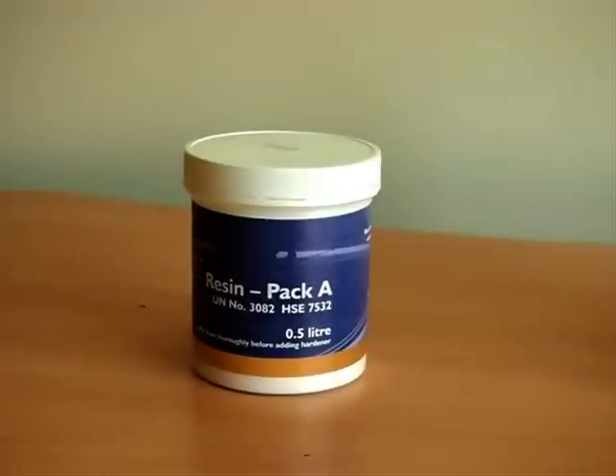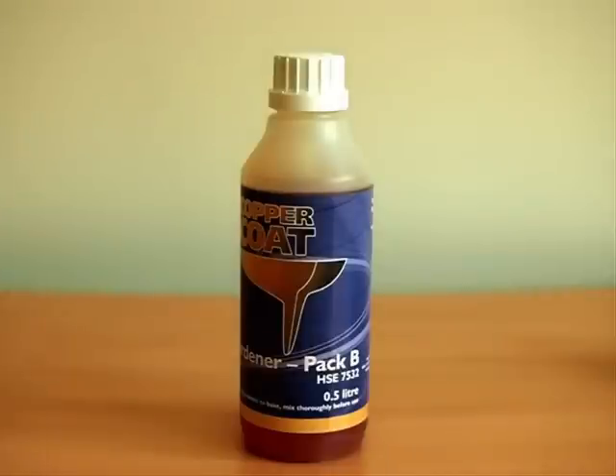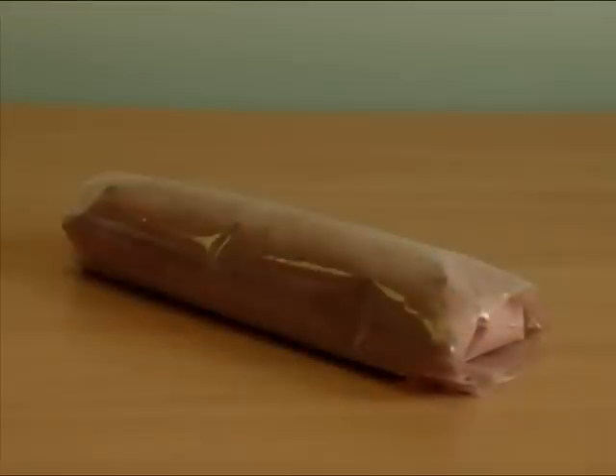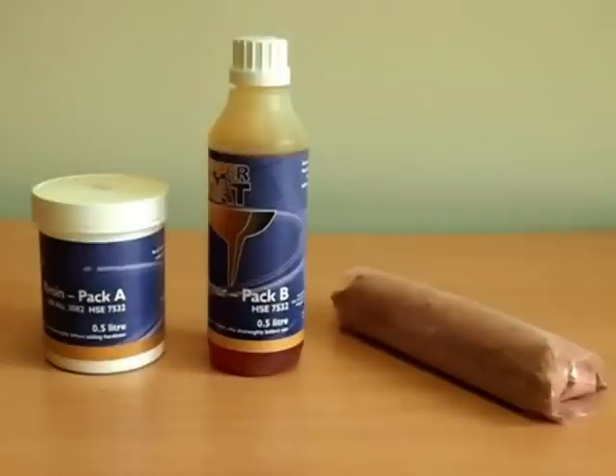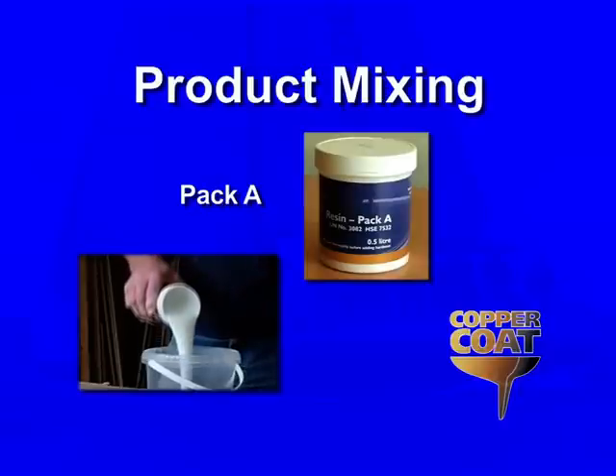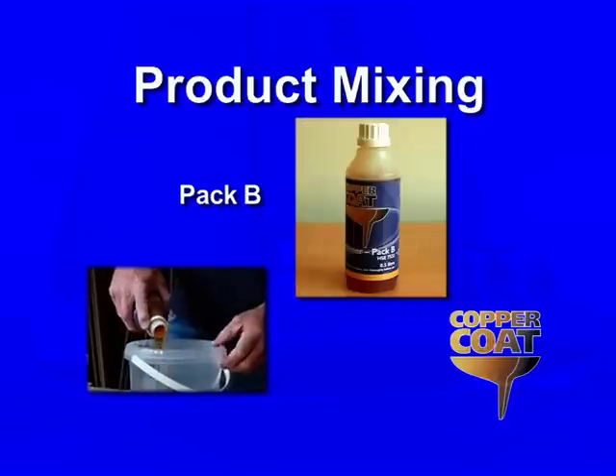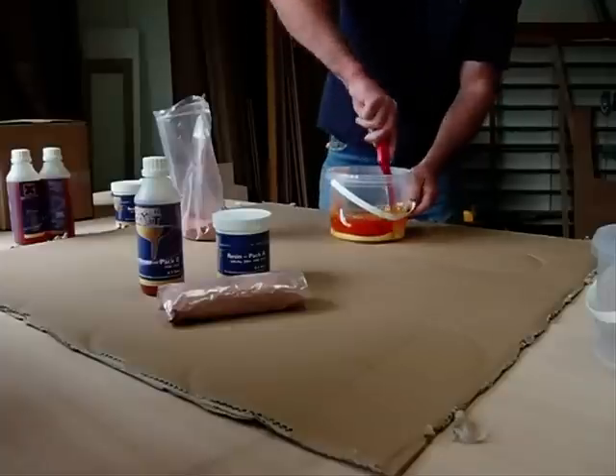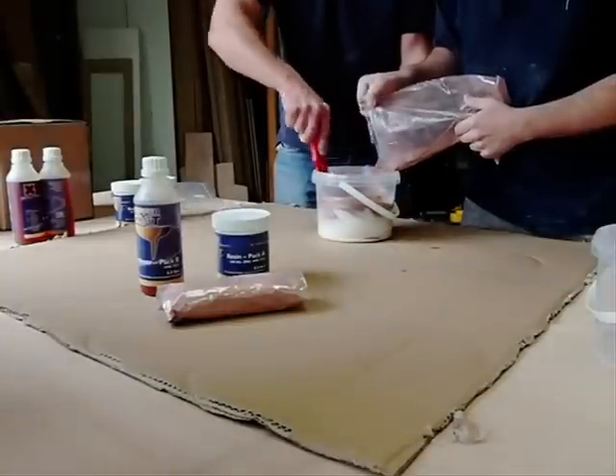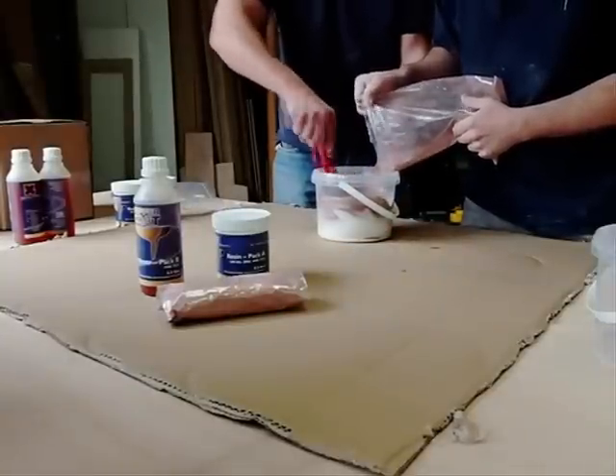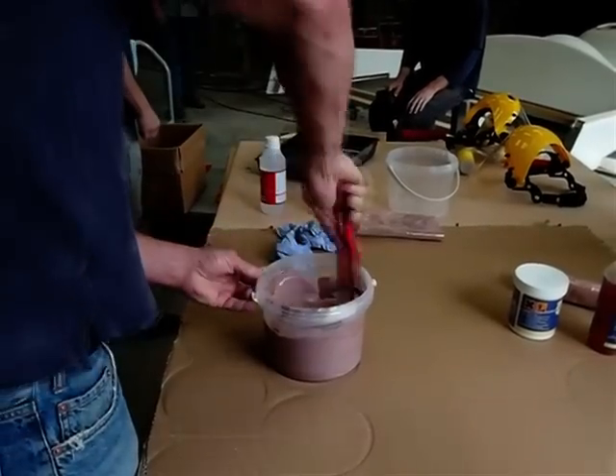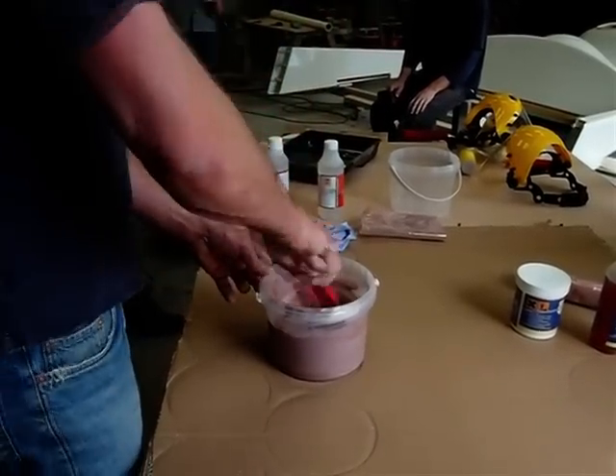Coppercoat is applied in 3 parts. Pack A is the white epoxy resin base, pack B is the brown coloured hardener, and finally pack C is the pure copper powder. Empty the contents of pack A into an appropriately sized plastic container and pour in the bottle of pack B. Stir these together thoroughly before adding the copper powder. Continue to stir until a fully homogeneous mix is obtained, with all the copper being held in suspension. Using the mixing stick, feel that no copper is resting on the bottom of the container.